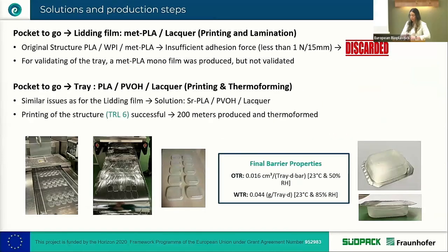Now I would like to go to the process, how we achieve to do these packagings. First, we demonstrate the Ferrero Pocket to Go. That was a peel solution where we first work with a substrate PLA base, met PLA with whey protein coating and PLA. As my colleague Kristina already explained, we faced some troubles with the substrate and the protein coating. We saw that the adhesion force between layers was insufficient. But later on, I will explain that with other substrates, we actually successfully did the lamination. Therefore, we discarded this solution and we went for a mono solution with a coating.